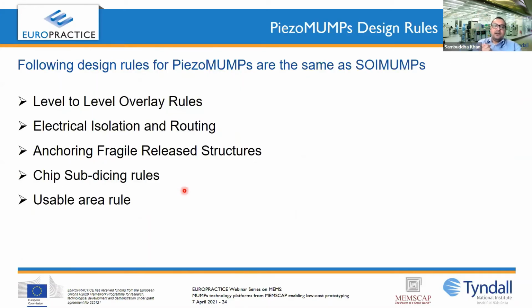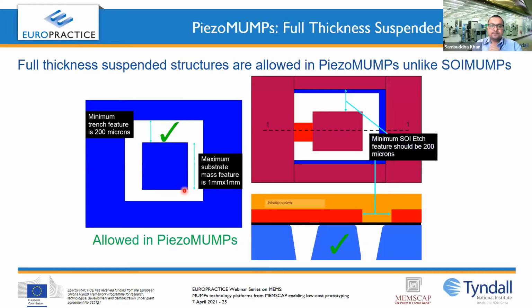These are the design rules that are almost the same as SOI MUMPs, that is level to level overlay, electrical isolation, routing, anchoring fragile structures, chip subdicing rules, and usable area rule. Almost the same as SOI MUMPs. There is a great difference between SOI MUMPs and PiezoMUMPs in terms of allowed structural constraints. For SOI MUMPs, as I already mentioned, thick structures are not allowed, but for PiezoMUMPs, suspended thick structures are allowed if the minimum trench feature is 200 micron and the minimum substrate, that is the mass size, is 1 mm by 1 mm or less.